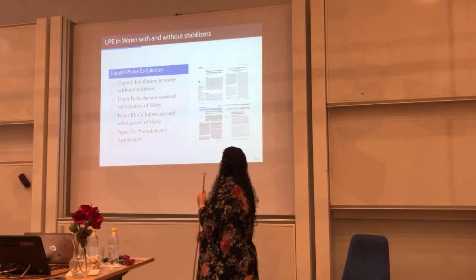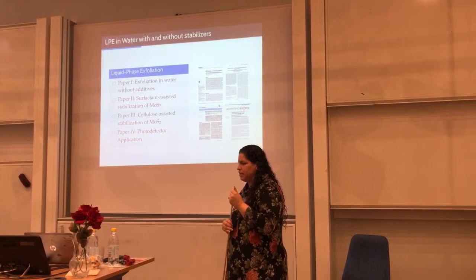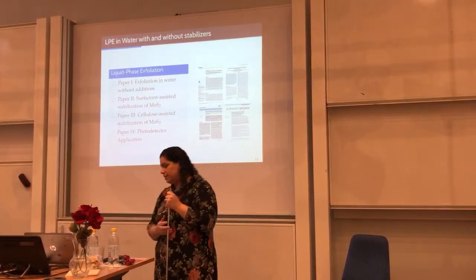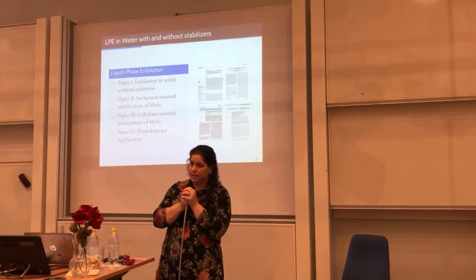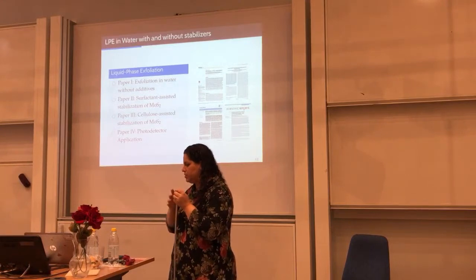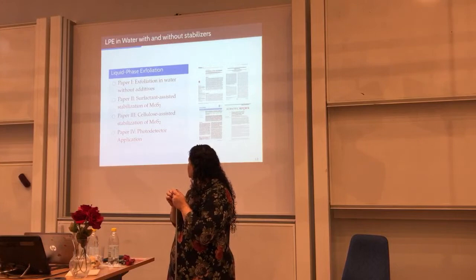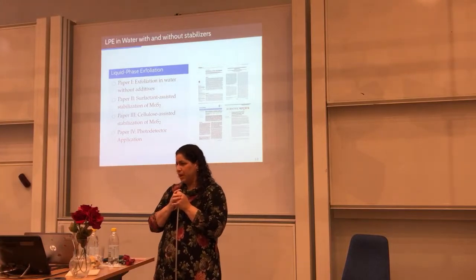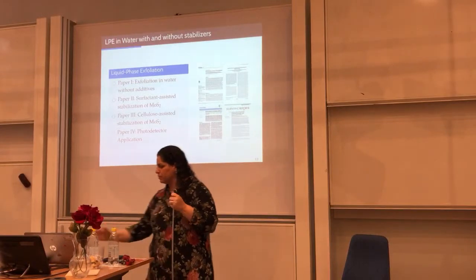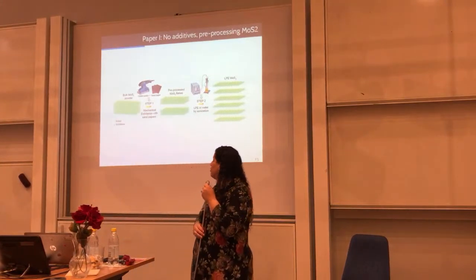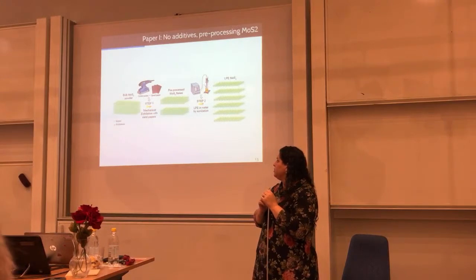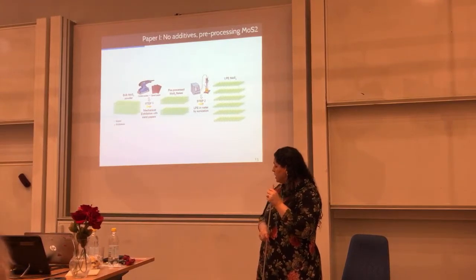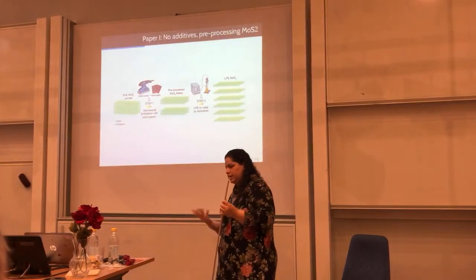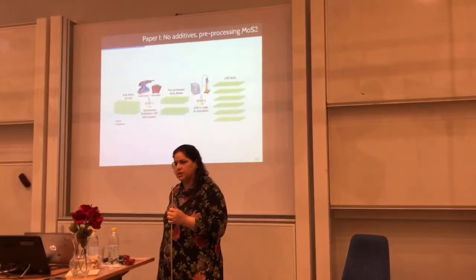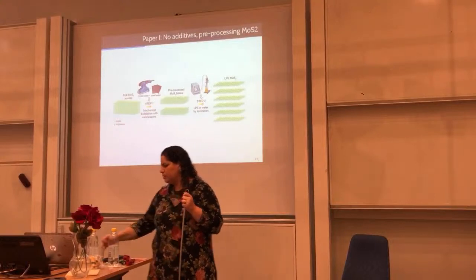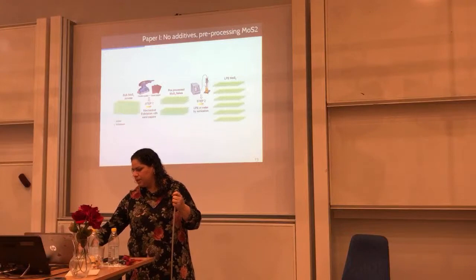So I discuss the findings of Ravin on a photodetector that he made by exfoliating the layered materials, the molybdenum, in nitric acid. That's why I don't focus on the exfoliation part of this work, because he used a different solvent. But what I want to show with this paper in this thesis is that, yes, it is possible to build devices out of exfoliated layered materials. Nowadays, devices have even been made fully printed, only with layered materials: using graphene as gate and source electrode, molybdenum disulfide as the semiconductor, and boron nitride, which is also a layered material, as the insulator. This was done by the group of Jonathan Coleman, by Kelly, and it's a Nature Communications publication.